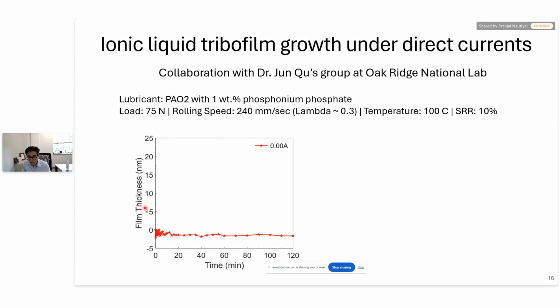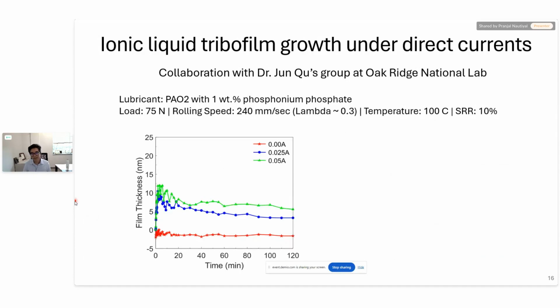Initially at 0 amp, without any current applied, we barely saw any tribofilm growth under these test conditions. It was a very thin film and hard to quantify using SLIM. However, when we applied 25 milliamp current, we clearly saw an acceleration in the growth of the tribofilm, right? We can see a thicker film formed much more rapidly, and then it sort of saturated towards the end of the 2-hour-long experiment. Then we further increased the applied current to 50 milliamp, and that produced an even thicker film.